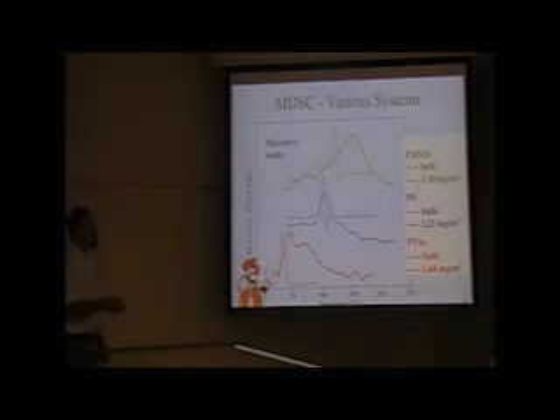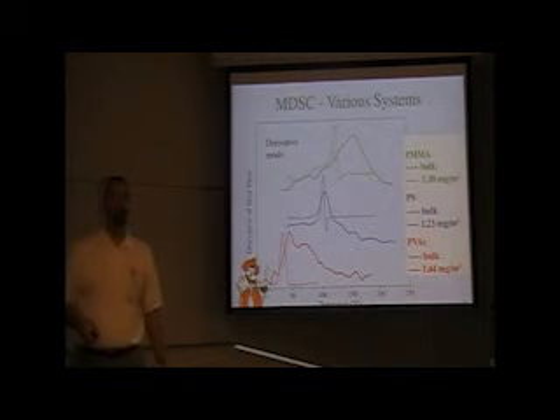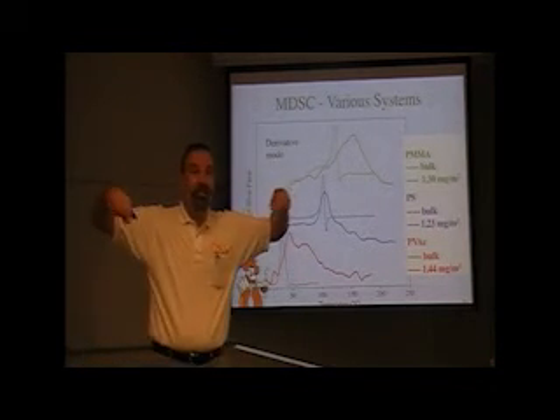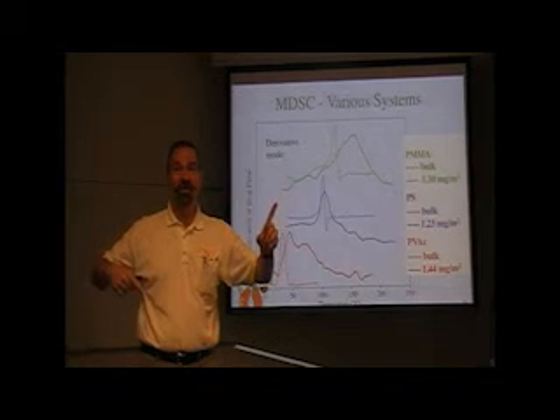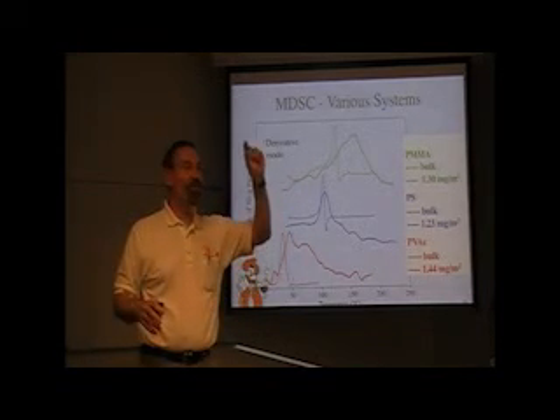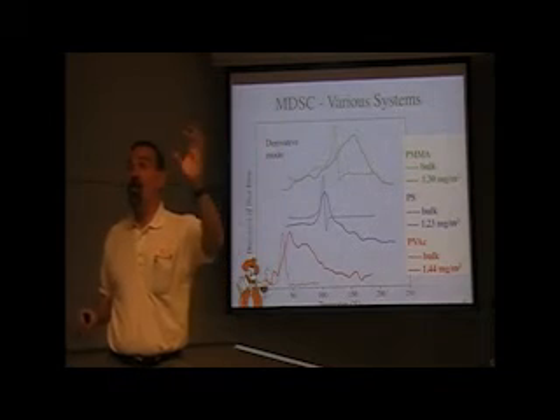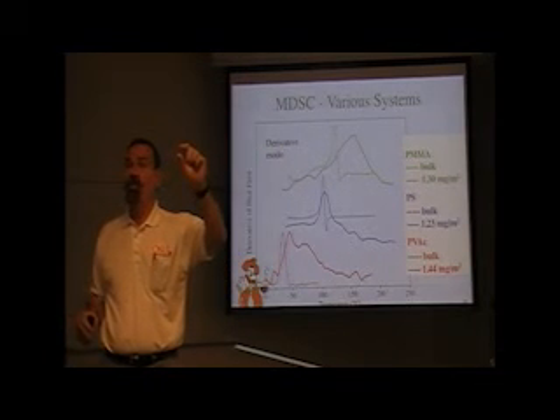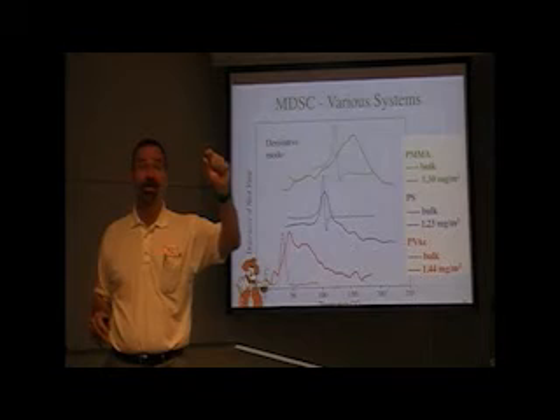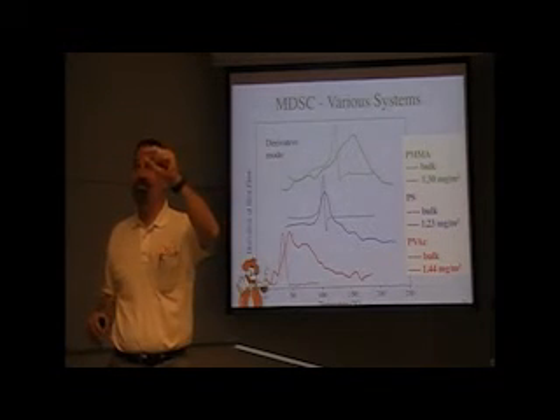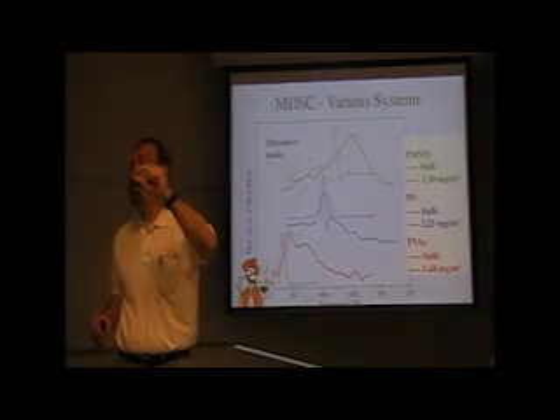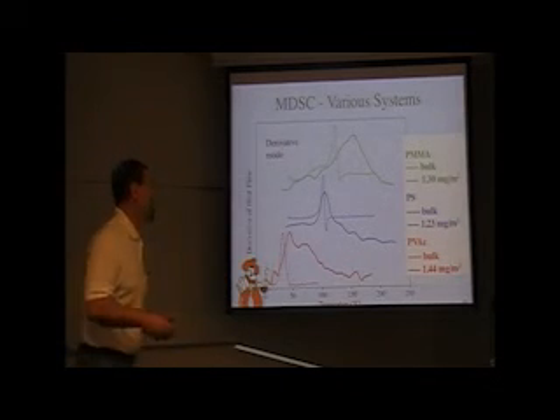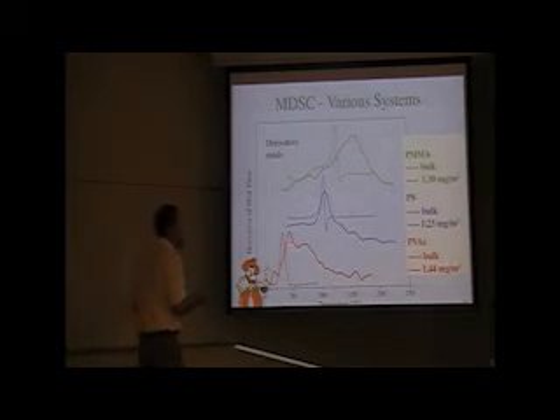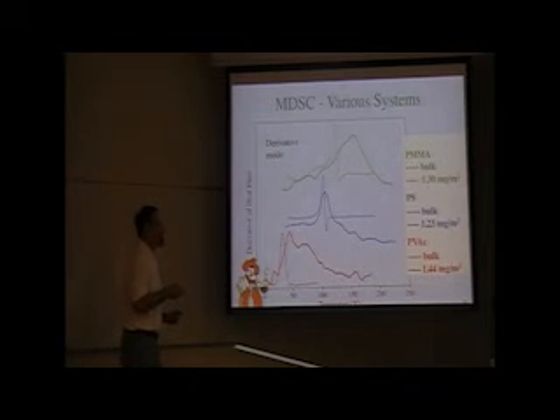And if you add more than this, and by the way, that's 1.44 milligrams per meter squared. So I have, on 1 meter squared of surface, about 1 milligram of polymer. If that was a uniform layer, how thick would that be? Well, if the density is about 1, it's 1.4 nanometers. That's really thin. It's really a small amount of material. This is really a surface effect. And by the way, when you get up around 1, you see that it starts to look kind of bulk-like. Not exactly bulk-like, but kind of bulk-like.